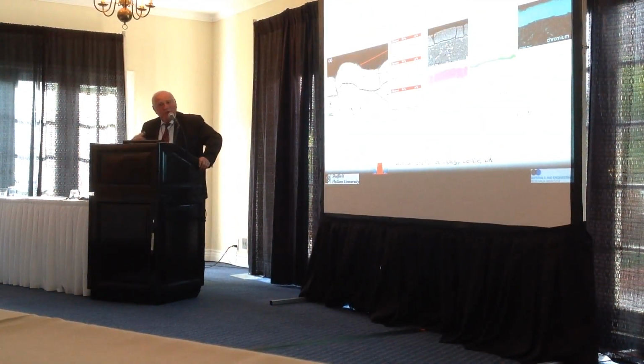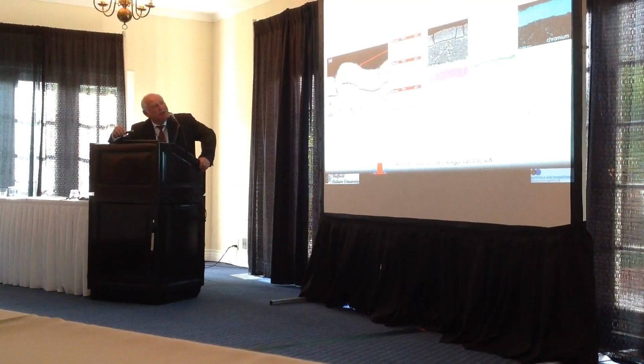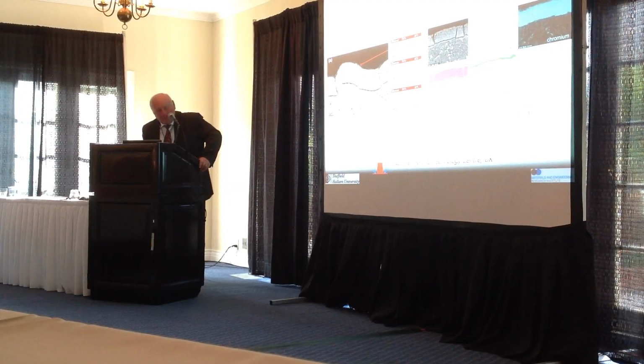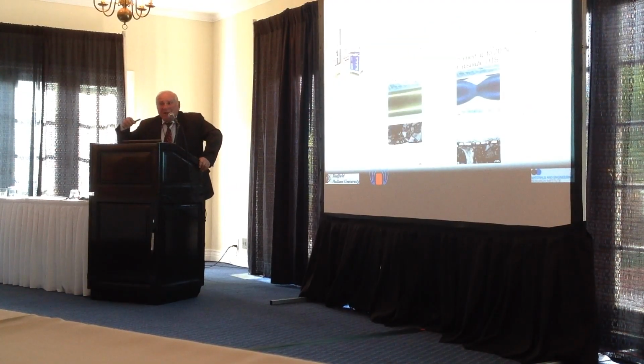It is very important to see how the high temperature oxidation resistance looks like. So after 2,000 hours, this is the oxygen map. You can see a very thin layer was only oxidized, and if you have some cracks and voids, they will be plugged by this oxide, so basically you protect very effectively the substrate with this coating. So the oxidation resistance was very high. That is a very interesting result.